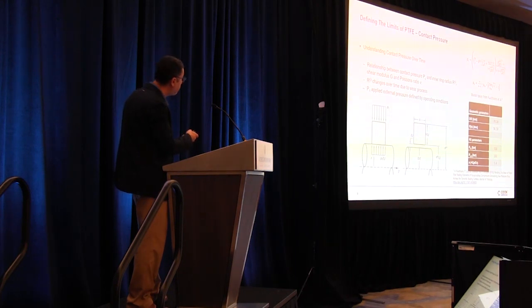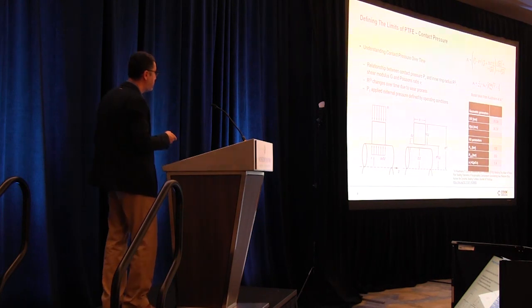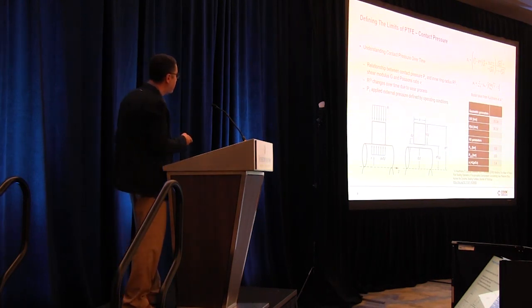Now I have a little bit of a complicated model here, but starting with the contact pressure, I'd like to give you a description of some issues we may have with PTFE. So here we have a model of a rod ring. This is the cross-section of a rod ring. In our model, we will use the geometrical parameters defining this rod ring geometry, which is the inner radius and the thickness and the axial length of the seal. And it's rubbing against the rod.